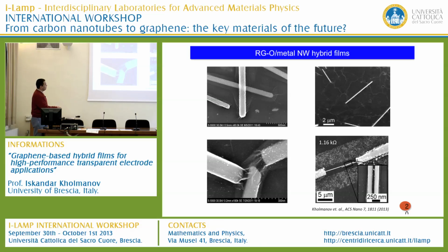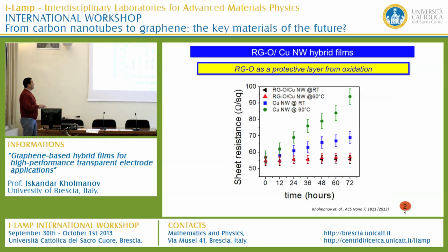And this is another example: two nanowire films that initially were not contacted, so there is no electrical conductivity. After that we covered them with the RGO film. Then we have electrical conduction through the two nanowires. So RGO, when it covers the nanowire film, increases the electrical conductivity.